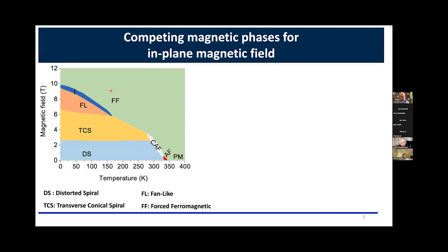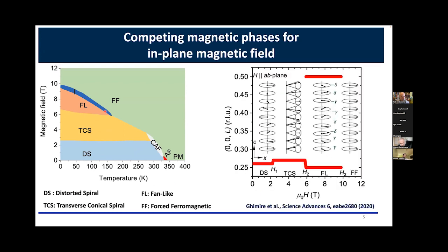We can see these 4 main magnetic phases here in the phase diagram for field in plane. The first one starts with the spiral state, and you apply a magnetic field in the plane, the spins start tilting in the direction of the magnetic field, and this makes a distorted spiral state. When the magnetic field increases above this H1 magnetic field, you're applying the field in the plane, but the spins find it easier to move out of plane. It's pretty interesting. But they tilt along the direction of the magnetic field, and what that does is it forms a spiral state called the transverse conical spiral state.